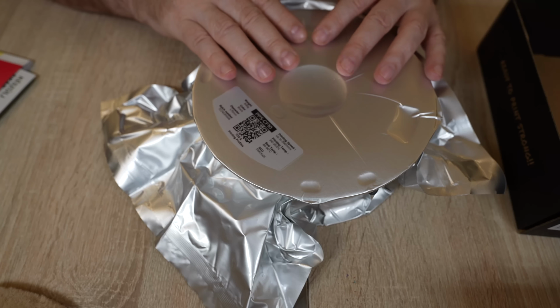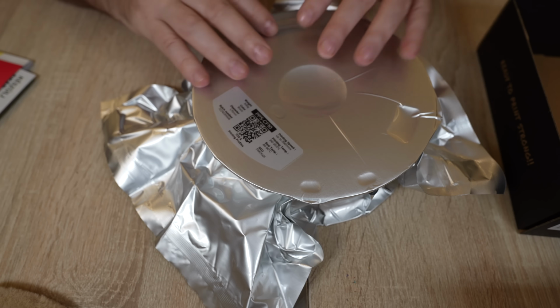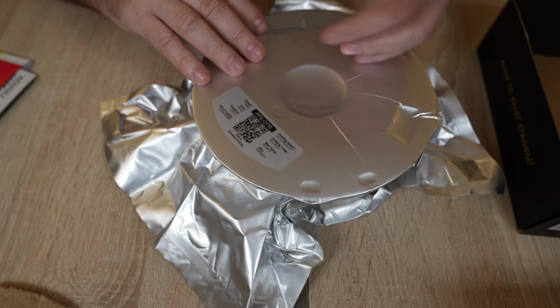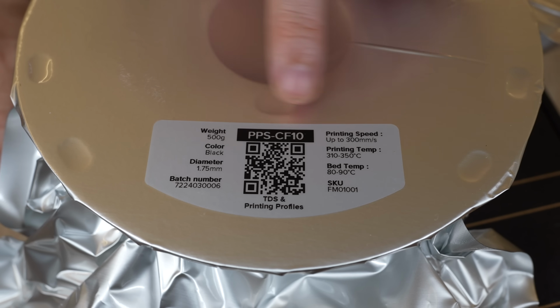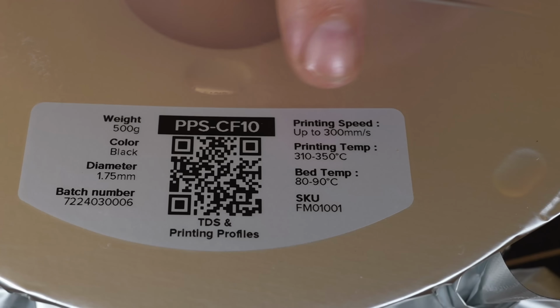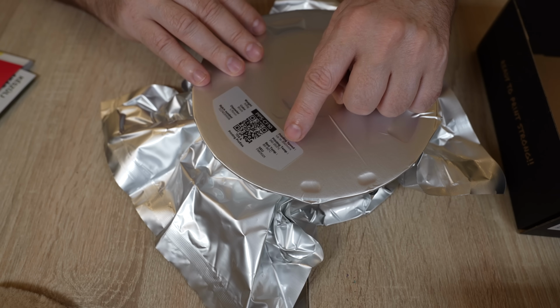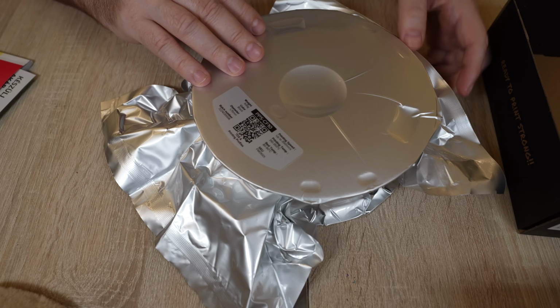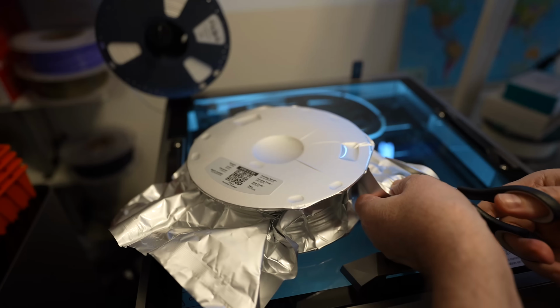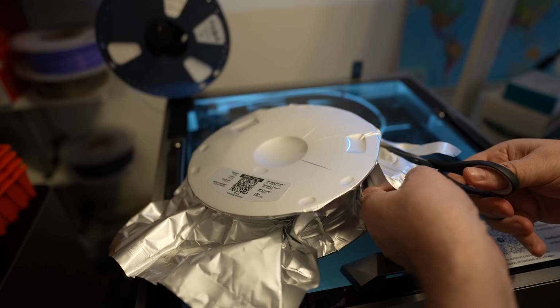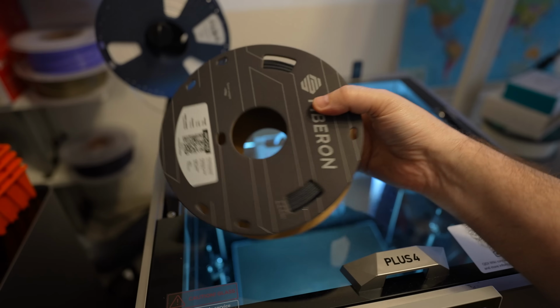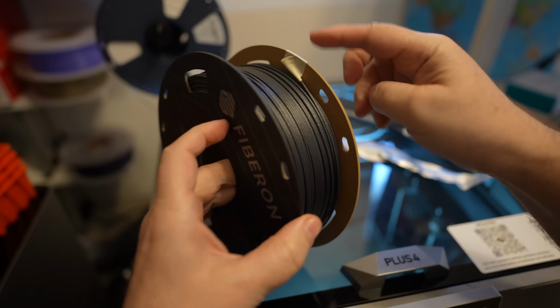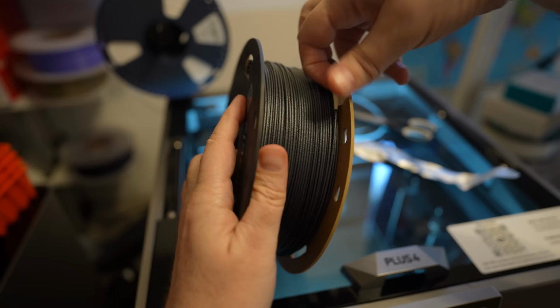This packaging is really good against moisture, but theoretically this material is less sensitive to it. And this is a half kilogram spool, and now I can see very interesting information. Printing speed up to 300 millimeters per second. And the bag is resealable, only on the smaller side. End of the filament is glued.